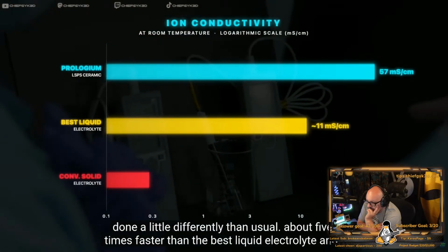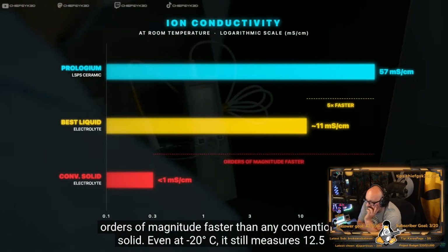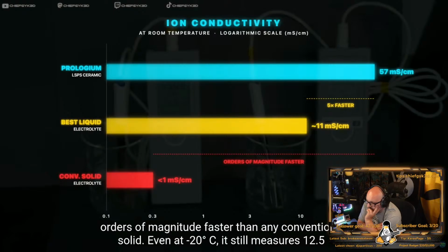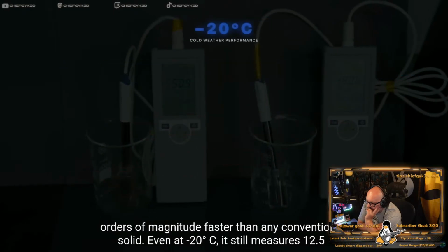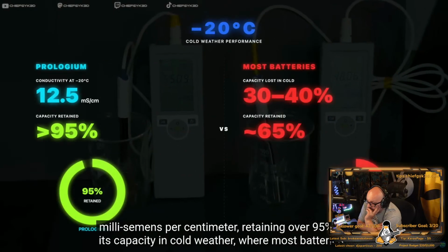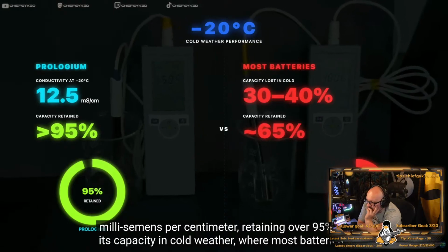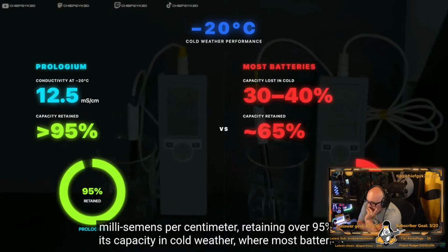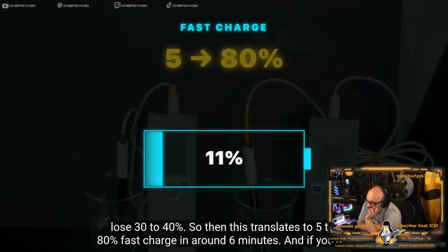About 5 times faster than the best liquid electrolyte, and orders of magnitude faster than any conventional solid. Even at negative 20 degrees Celsius, it still measures 12.5 millisiemens per centimeter, retaining over 95% of its capacity in cold weather, where most batteries lose 30 to 40%.